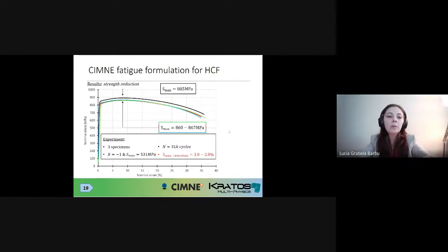And what we wanted to see is, if you apply a determined number of cycles, which we decided together is going to be 31,000 cycles, and then you break the sample monotonically, we were interested in finding out if the maximum level of stress attained by that specific specimen after having applied 31,000 cycles was the same as in the beginning, the same as for the virgin material, or not.